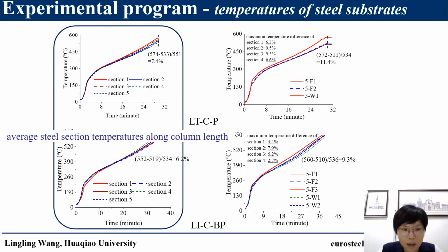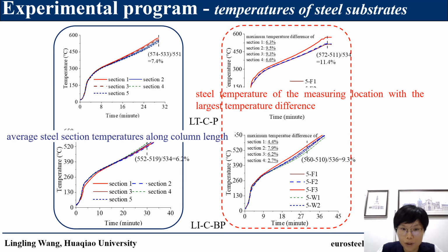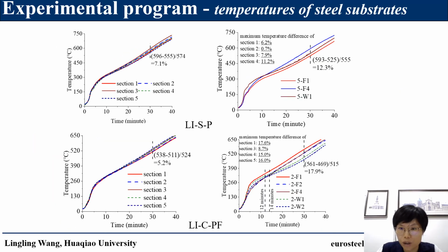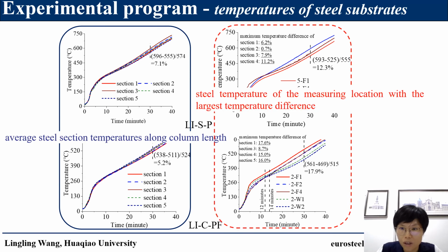These figures present average steel section temperatures along column length and the individual steel temperature measuring location with the largest temperature differences for unloaded column specimens. Along the column length, there are some differences in average cross-section temperature. However, the differences were relatively small, suggesting that it is acceptable to assume a uniform temperature. Temperature differences in the cross-section seem to be high.